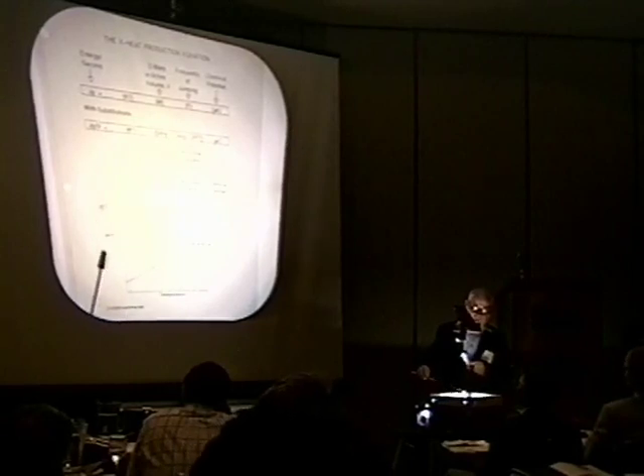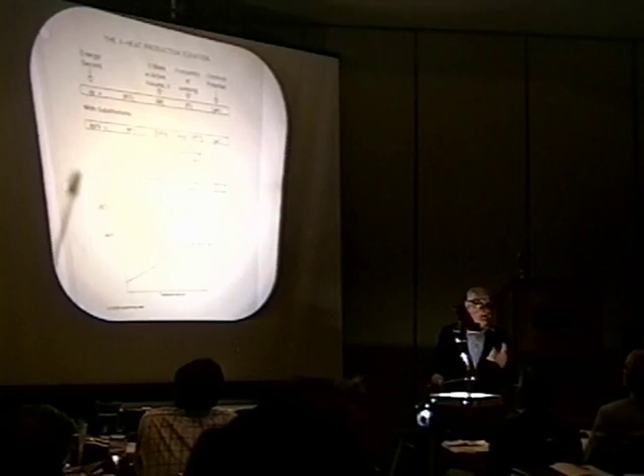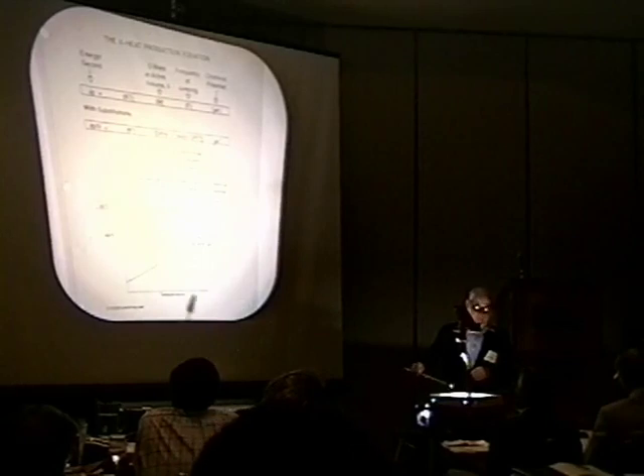And if we plot this production equation, this is the watts per cubic centimeter against the temperature, we'll see this kind of curve. It's a fairly rapidly rising curve. All three elements affected, but primarily the temperature element. And this curve will extend into, for palladium, hundreds of degrees C, and it will extend into the kilowatt range.